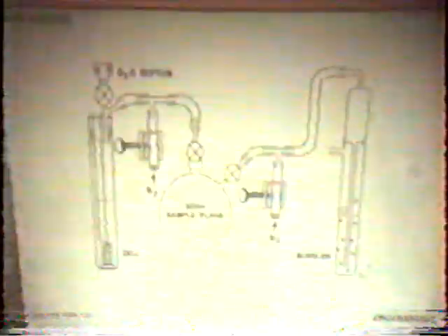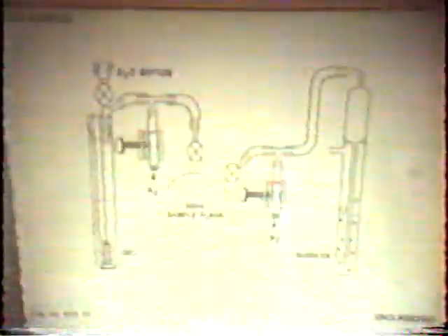But in addition, doing electrolysis, this flask is generating enough gas to flush it out every 73 minutes. So this flask is being flushed out 19 times a day by the electrolysis gases that are flowing. So it is self-flushing. It's always flushing itself out 19 times a day. And we would never disconnect it until it was on at least 2 days. So it always had an opportunity to be self-flushing at least 38 times before we disconnected.